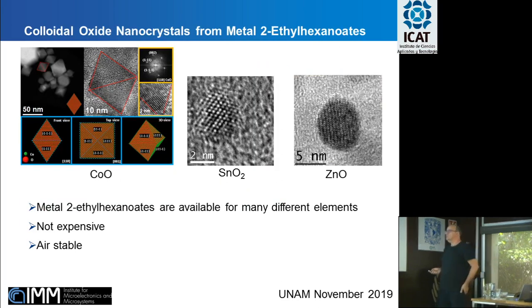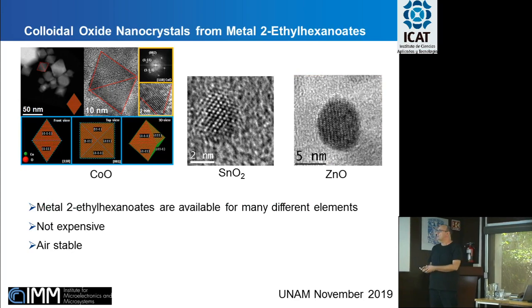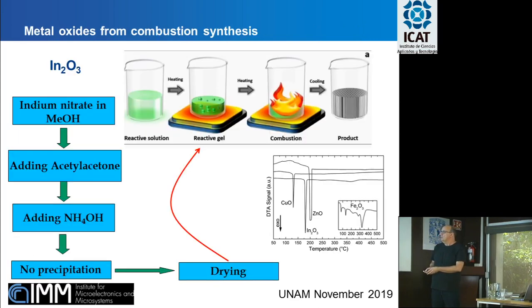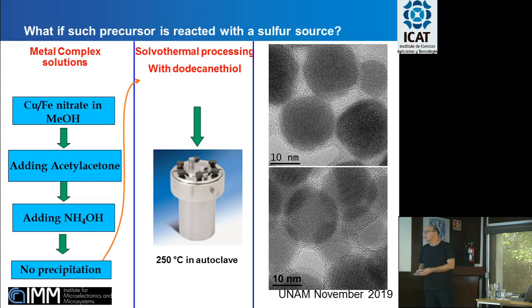This is also possible for the other precursor that we have seen before. Metal 2-ethylhexanoates can be used for making nanocrystals, colloidal nanocrystals, not only thin films or powders. We can use precursors like those used for indium oxide thin films for making metal oxide powders from combustion synthesis. Or we can make the same synthesis as before, but if we do our solvothermal treatment in a sulfur source like dodecanethiol, we get these copper sulfide nanocrystals.